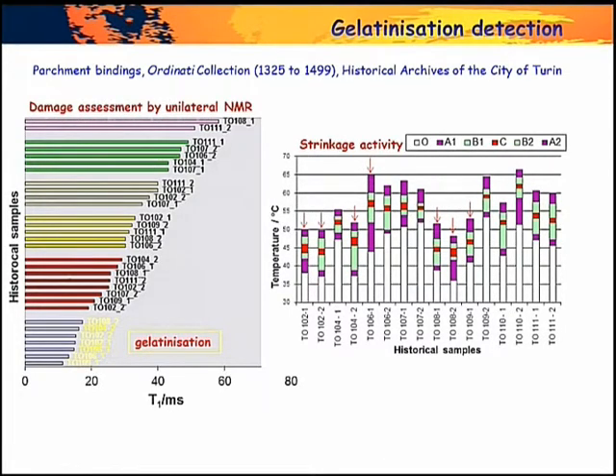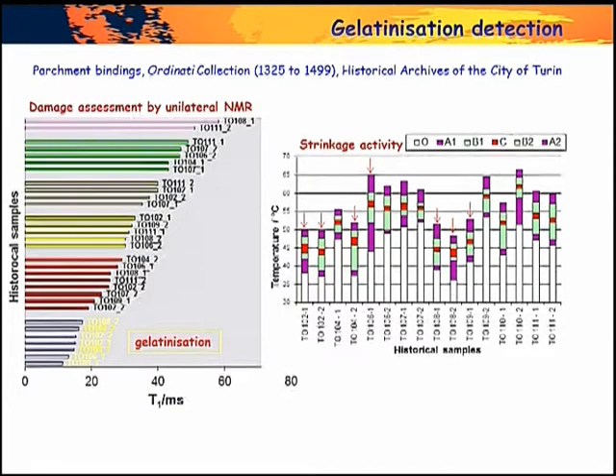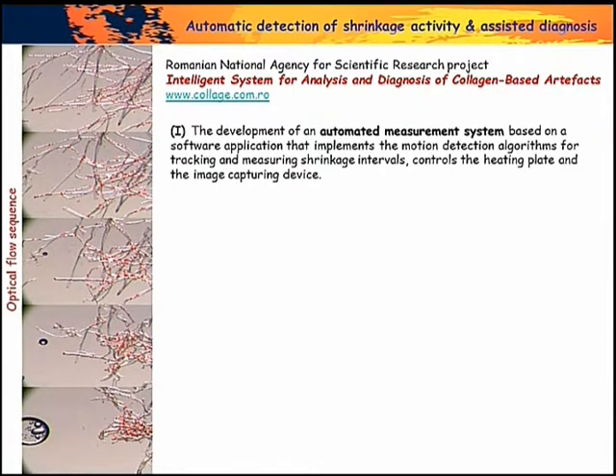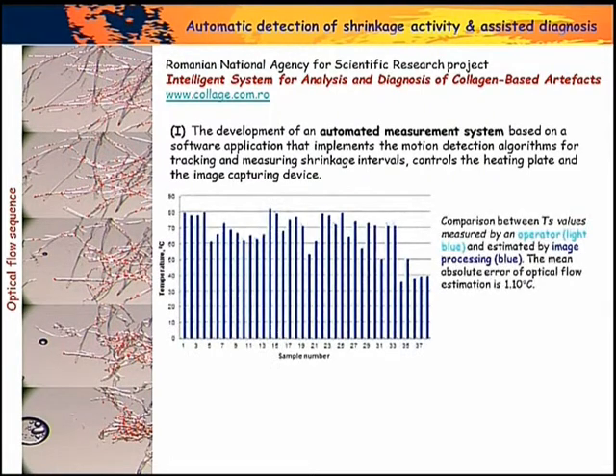This is the correlation that we found between gelatinization, in a case study of parchments that were studied using all the methods I mentioned before. We can see that the gelatinization we found by nuclear magnetic resonance was also found by measuring shrinkage activity. As I told you, the challenge now is to develop a system for the analysis and diagnosis of collagen-based artifacts. This means the development of an automated measurement system based on a software application that implements motion detection algorithms for tracking and measuring shrinkage intervals, and controls the heating plate and the image capturing devices.